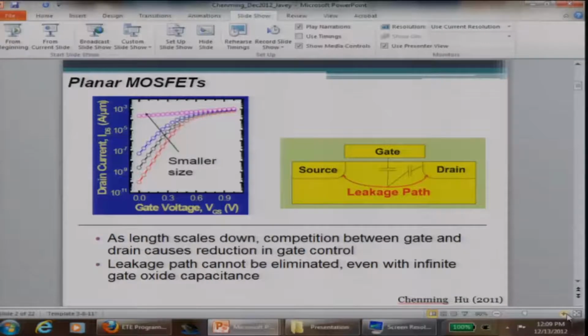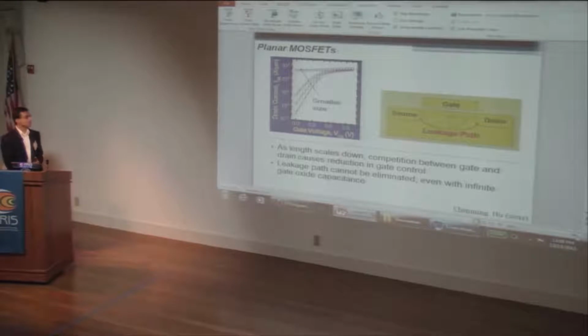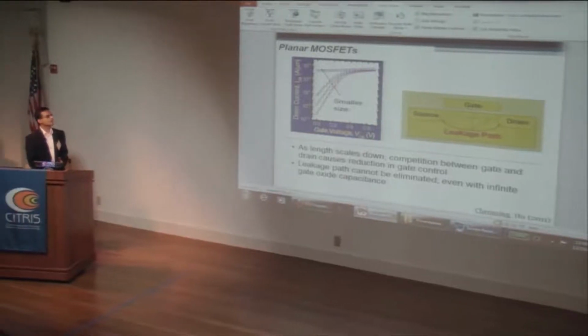For a long channel device, the region near the drain is controlled by the drain, but that's fine because far away from the drain, the channel and the source region, the barrier to the source, are all controlled by the gate. So in a long channel device, no problem. You're fine, you have a nice switch. As you bring the drain closer and closer to the source, now you can see that we have a problem. Right at the surface, close to the gate, the gate is still winning. But as you go deeper and deeper into your material, you get further and further away from the gate, but you're still pretty close to the drain. Drain wins. And here, qualitatively, you can see the effect. You go from a good switch with good switching behavior to effectively a resistor.